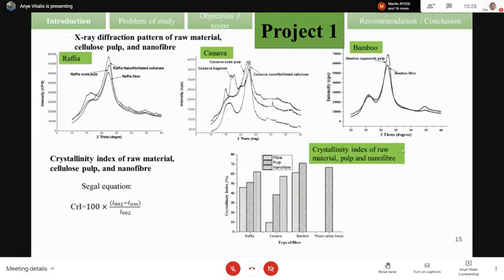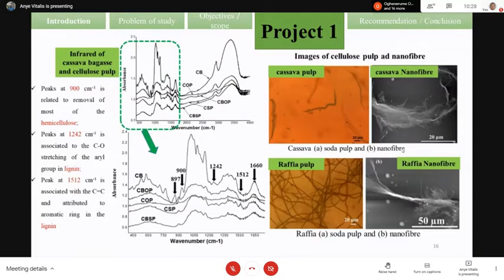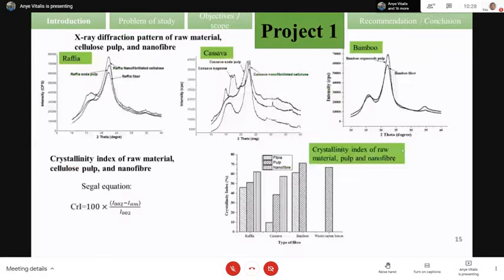We realize that by applying the pulping process on nanofibrillated cellulose, there is a significant improvement of the crystallinity index, which shows that there is a removal of the amorphous part in our bamboo-based cellulose material. We also studied the functional group by using FTIR, and we realize that from the raw material to the pulp and the bleaching stage,